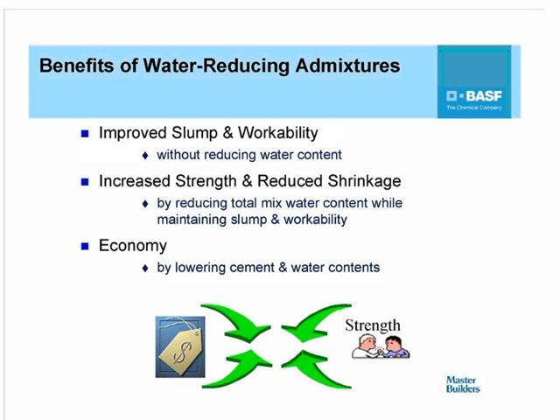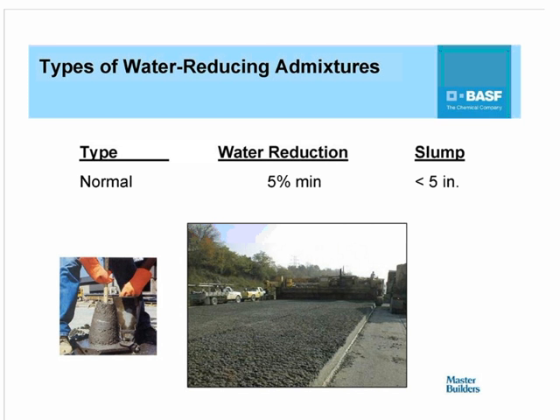Now, the main benefits of water-reducing admixtures can be summed up under these three bullets, part of the reasons why they're used. As I indicated earlier, the main purpose is to improve slump and workability of the concrete, and this can be achieved without necessarily reducing the water content of the concrete. They can also be used to increase strength and reduce the drying shrinkage of concrete by reducing the total mixed water content while maintaining the slump and workability of the concrete. And finally, they can also be used to economize the mix by lowering the cement and water contents without necessarily affecting the strength and workability of the concrete.